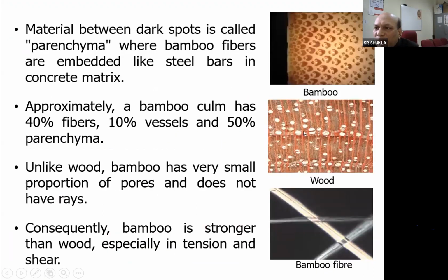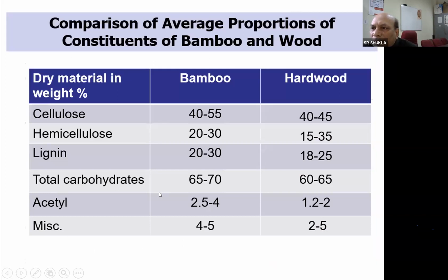And here the wood structure and bamboo structure have been compared. We know that bamboo is made of around 40% fibers, 10% vessels, and 50% parenchyma cells, which is the material between the fibers. The main difference between the bamboo structure and the wood structure is that wood contains these kinds of holes, called vessels, but these are absent from bamboo. And bamboo fibers are quite long compared to wood fibers. That is why bamboo is comparatively stronger than wood.